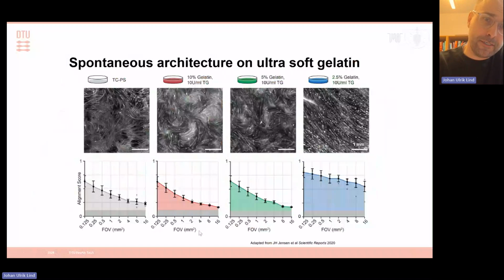If you culture skeletal myoblasts, then you fuse them into skeletal muscle fibers. These are muscle fibers that you can see here. If you just culture them in a regular petri dish, what you see is that you get localized areas where the fibers are pointing in one direction, but overall it's randomly organized. So if you zoom in very locally, you have a high alignment score, but if you go out broadly, then you have random alignments. That's also true if you culture cells on soft gels. You get some local domains that are highly aligned, but overall you don't have any control.